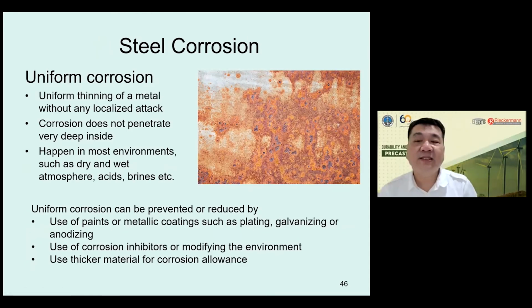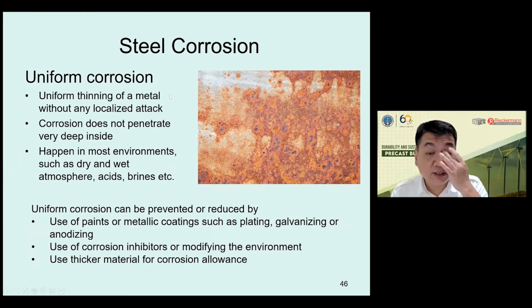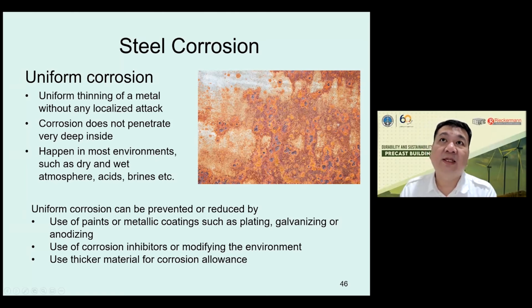And then, okay, for the steel corrosion, this is the uniform corrosion. This is normally what we see in the steel building, uniform corrosion, which is a uniform thinning of metal without any localized attack. We can see some part is localized. Actually, that is considered pitting, but when the overall part is corroded, we can still consider it uniform corrosion. And this is normal and still okay when we have very thin. Normally for uniform corrosion, we can protect using coatings, plating, galvanizing, or anodizing, or using corrosion inhibitors, or even anodic protection. Or we can just increase the thickness of our structural member.